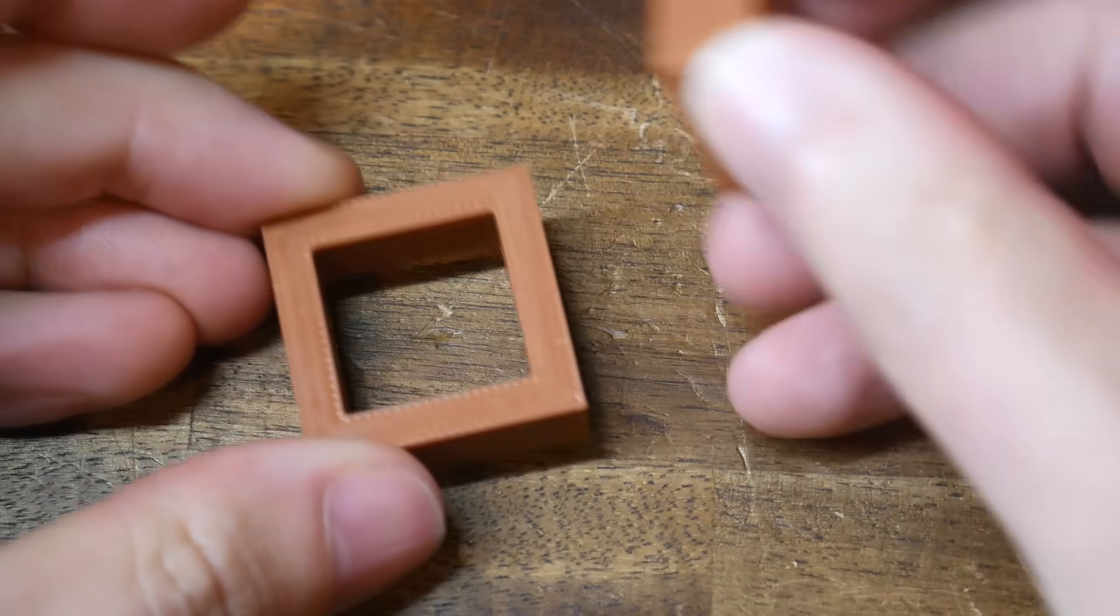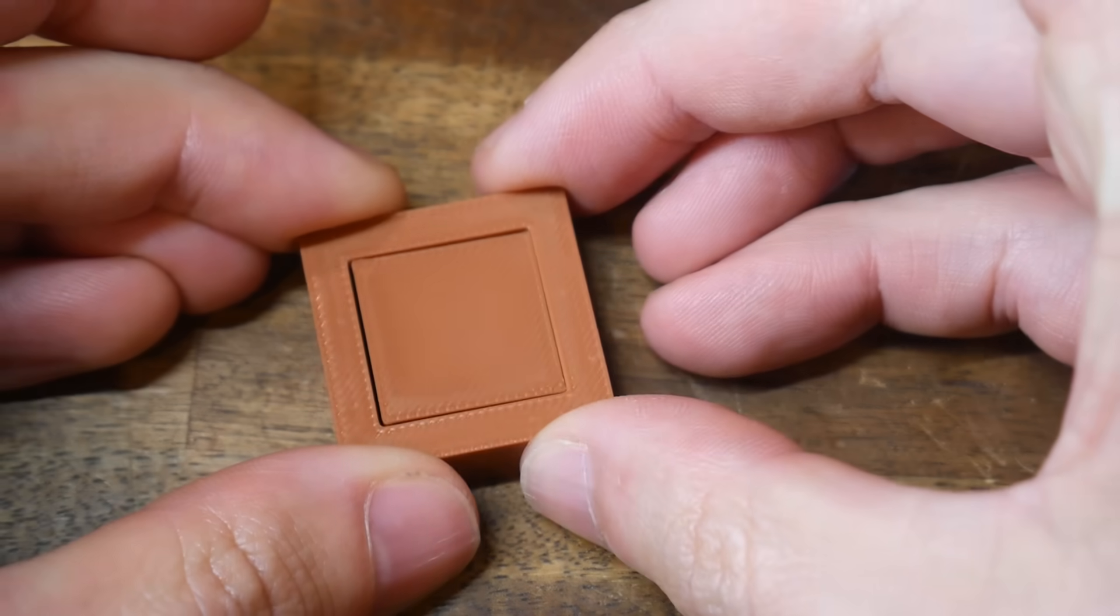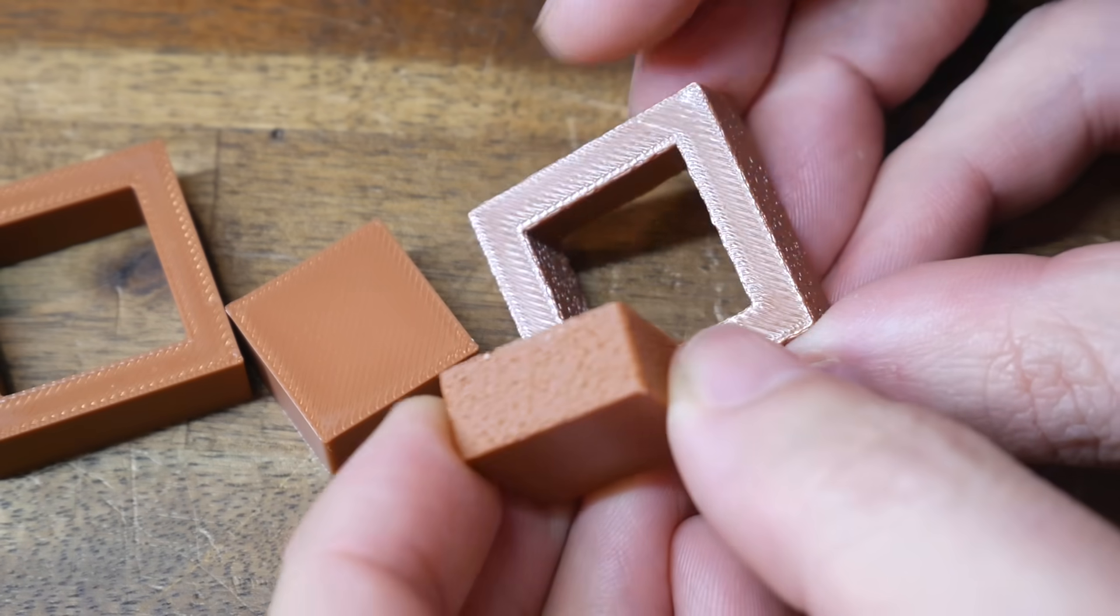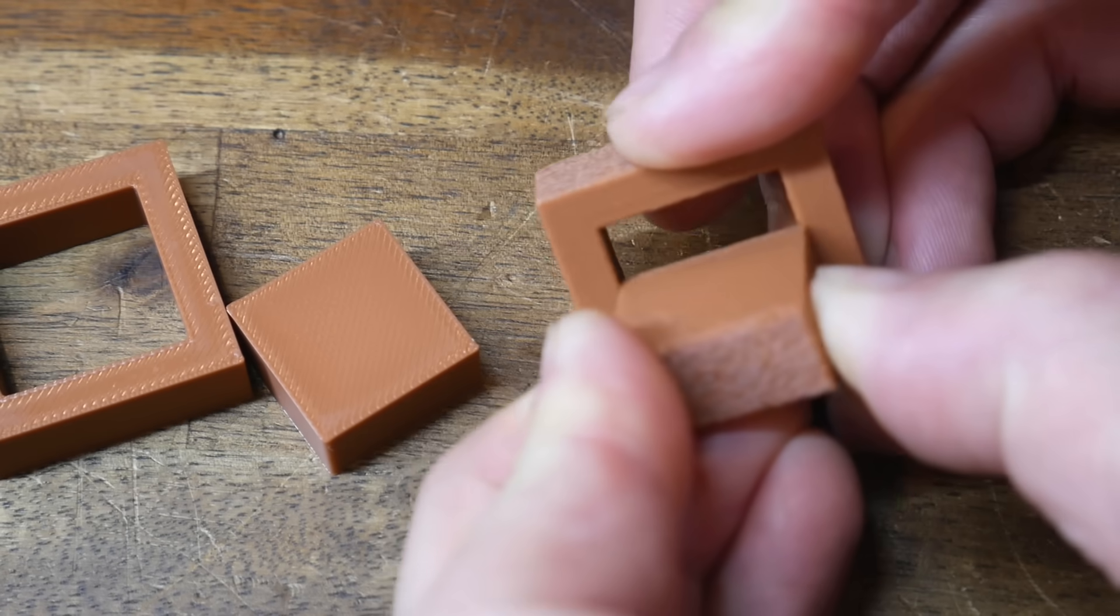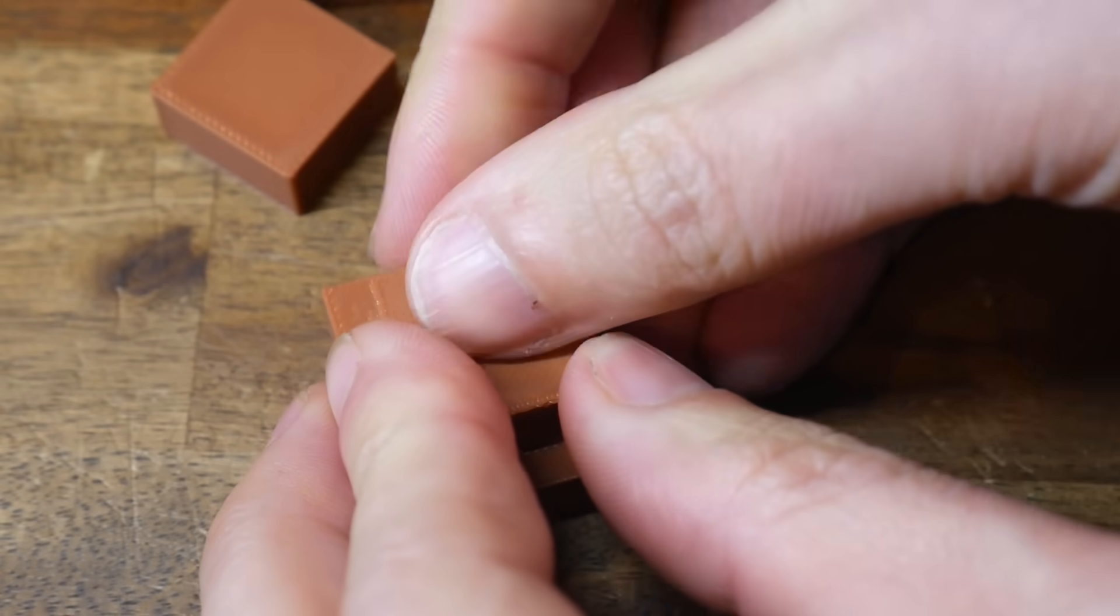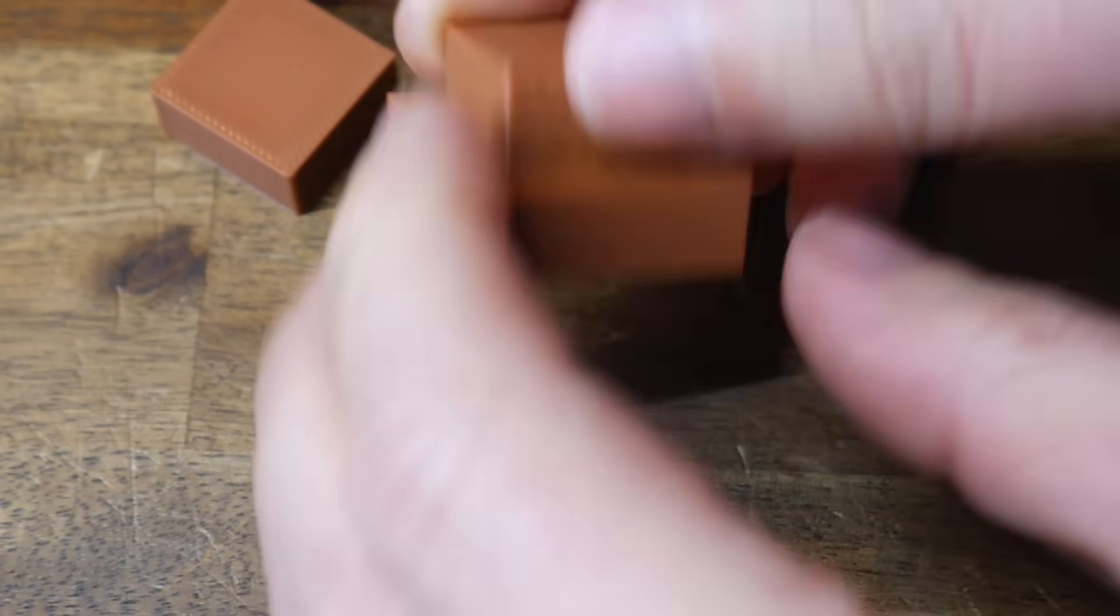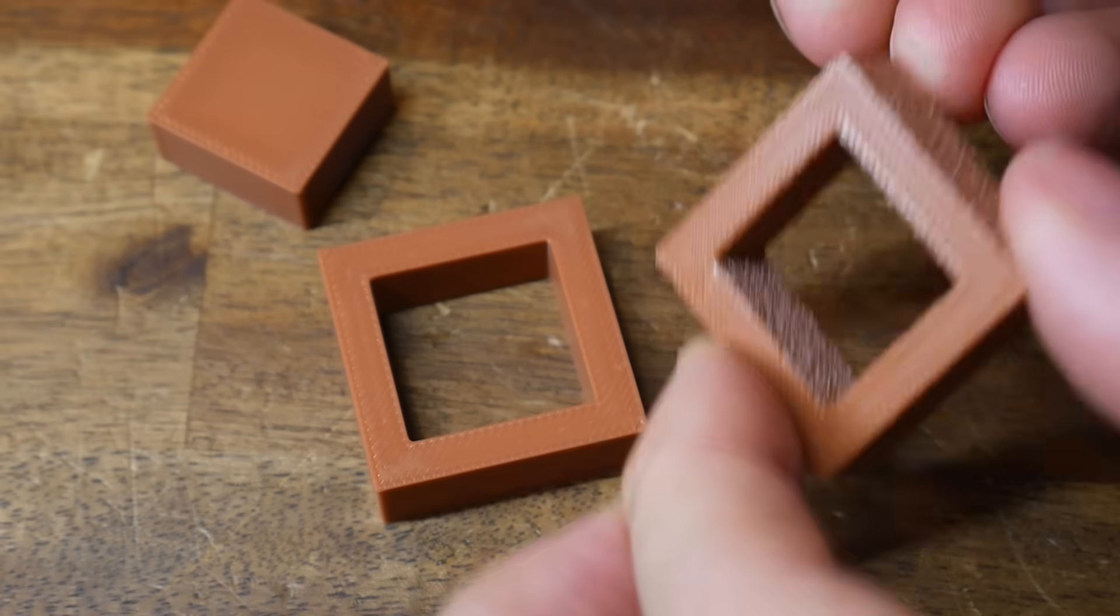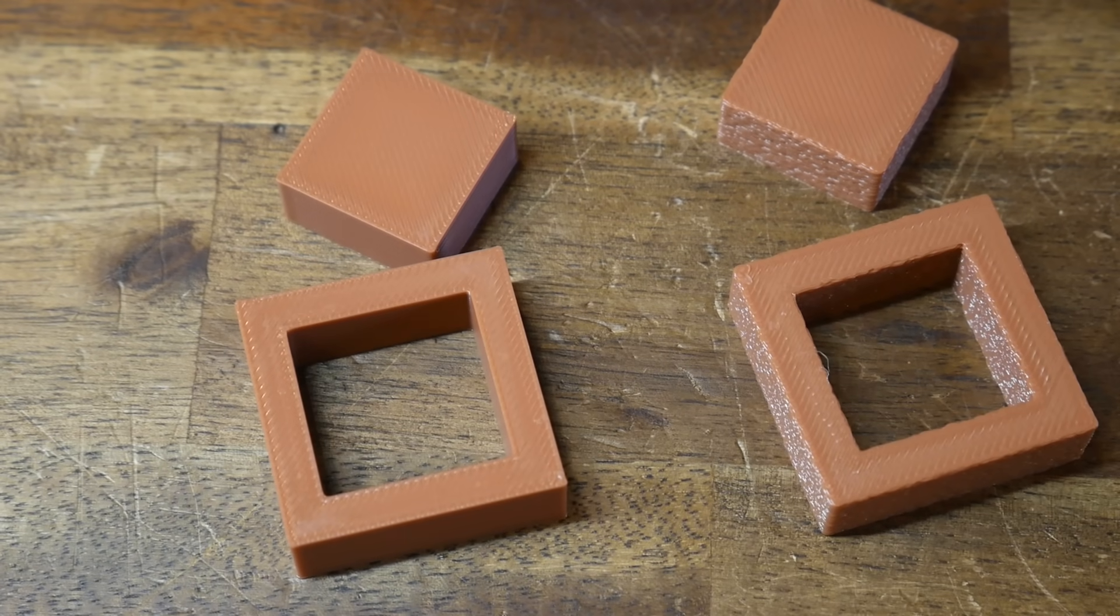Our other major problem is that we're decreasing the dimensional accuracy of the part. Consider this simple test piece designed to have a snug fit. Now let's compare a version printed with fuzzy skin. As we know, we've added thickness to the external perimeters, so the parts no longer fit. Even if we remove the texture from the internal cutout, the external fuzzy skin on the smaller part still prevents it from fitting. So to make sure fuzzy skin parts fit, you would need to shrink the exterior walls by the thickness of the fuzzy skin you intend to apply. This of course can be done, but now it's no longer an option that doesn't require CAD.